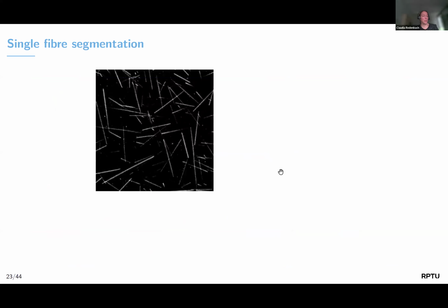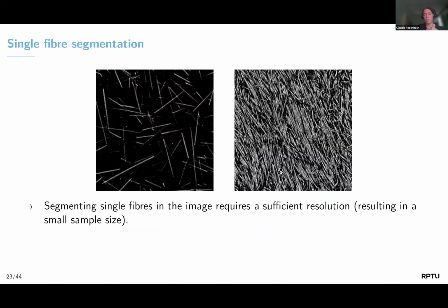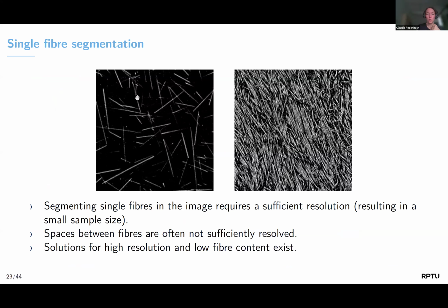Now I said you need a single fiber segmentation to be able to run that protocol. If you look at an image like this, with very high fiber density, it's hardly possible to get that segmented. So in particular, in practice, if you want to fit the length of the fibers, you have to make a compromise regarding resolution, and then spaces between the fibers may be poorly resolved. For fibers of that kind here, so very low density and high resolution, that's doable, but here it can get hard.